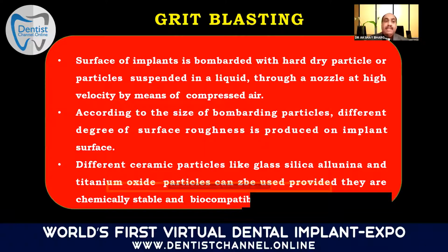Grit blasting. The surface of an implant is bombarded with hard, dry particles, or particles suspended in liquid, through a nozzle at high velocity by means of compressed air. And you have different types of materials: ceramic particles, glass, silica, alumina. The problem is that if the implant is soft and not a strong alloy, you can sometimes have contamination of these particles remaining on the surface and getting embedded into the implant surface.